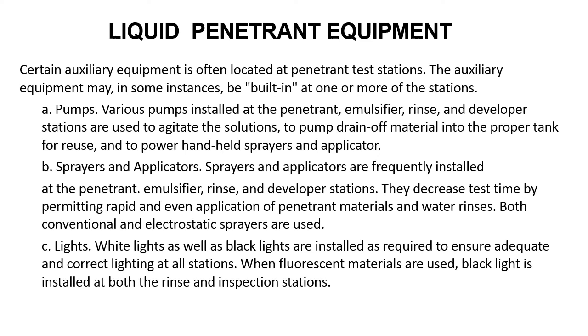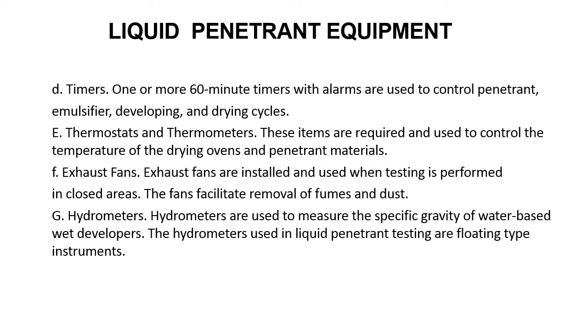Sprayers and applicators are frequently installed at the penetrant, emulsifier, rinse, and developer stations. They decrease test time by permitting rapid and even application of penetrant materials and water rinses. Both conventional and electrostatic sprayers are used. White lights as well as black lights are installed as required to ensure adequate and correct lighting at all stations. When fluorescent materials are used, black light is installed at both the rinse and inspection zones. Timers: one or more 60-minute timers with alarms are used to control penetrant, emulsifier, developing, and drying cycles. Thermostats and thermometers are required to control the temperature of the drying ovens and penetrant materials.